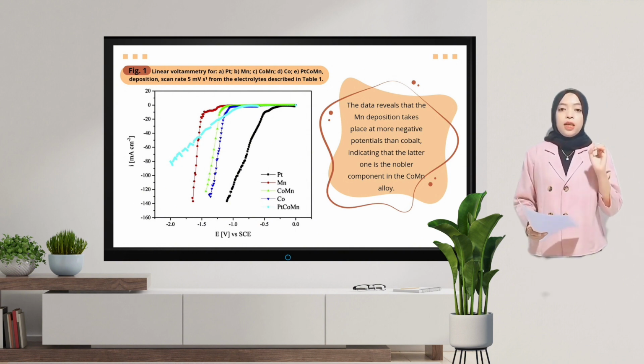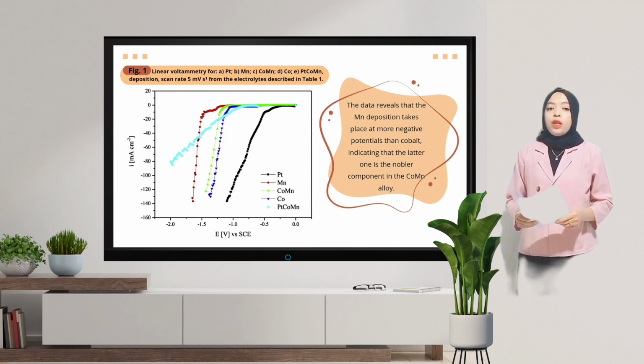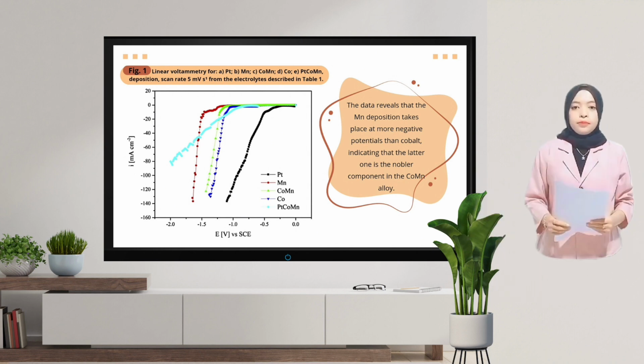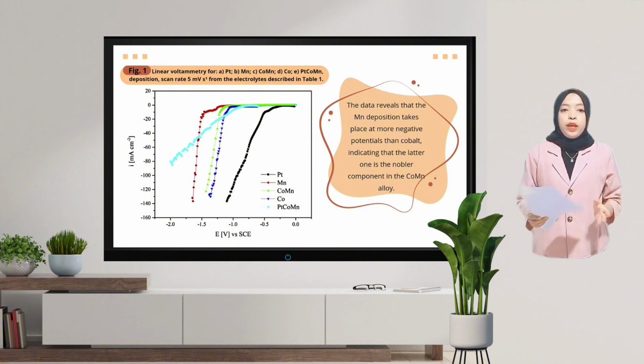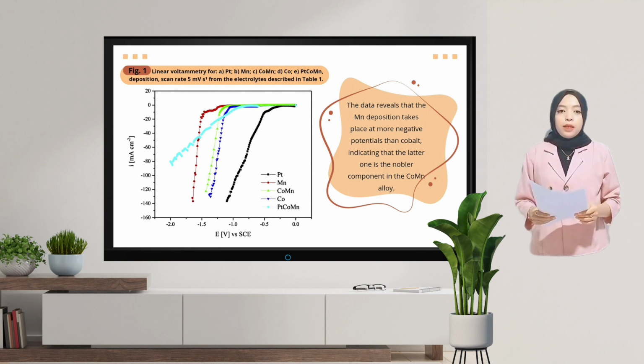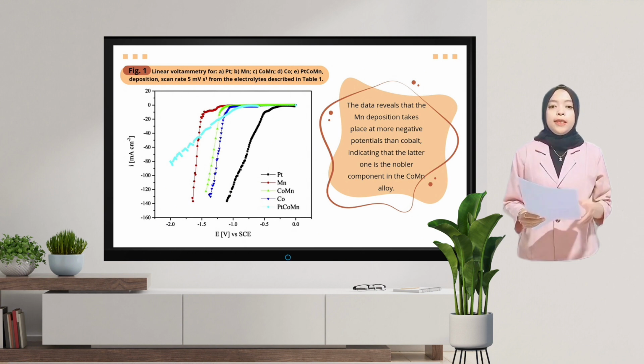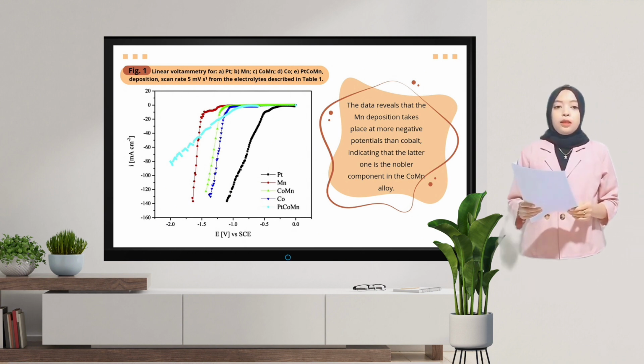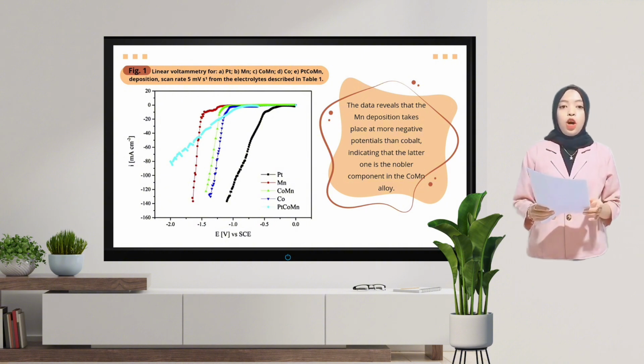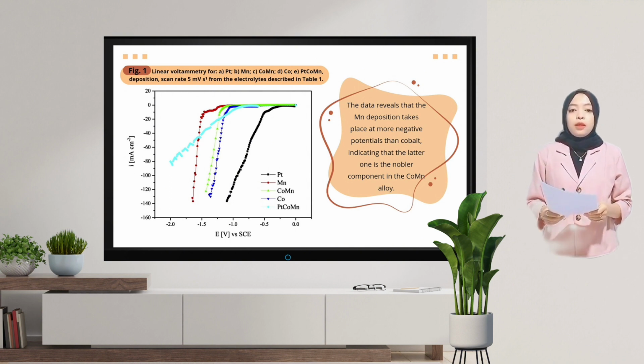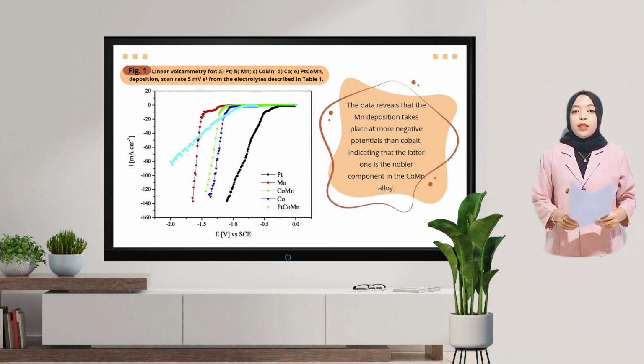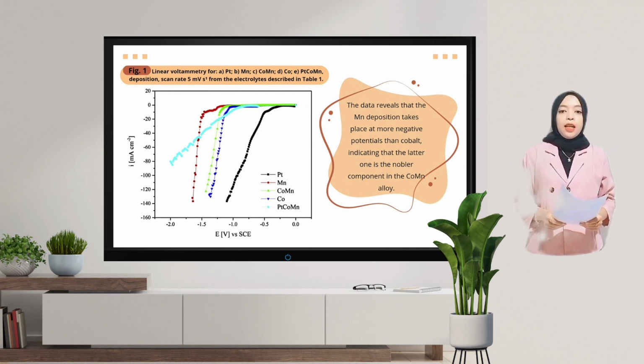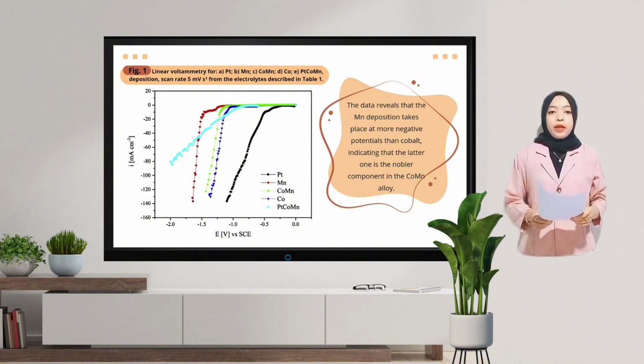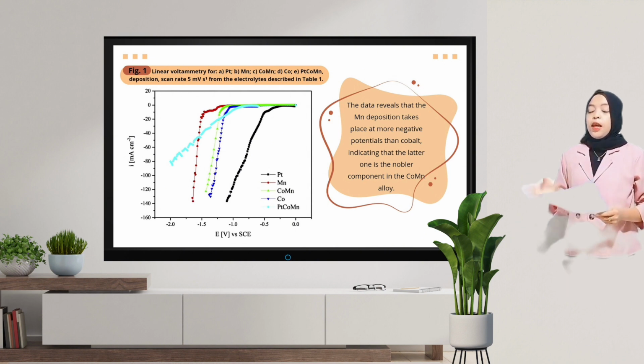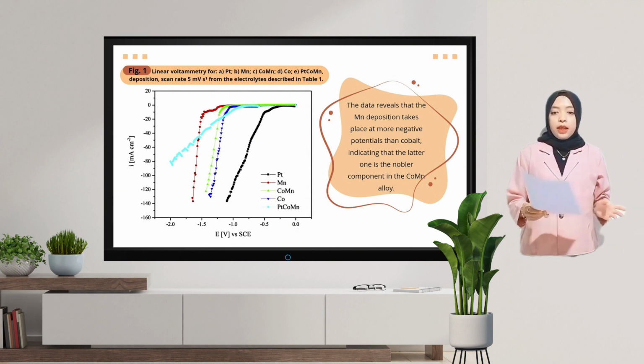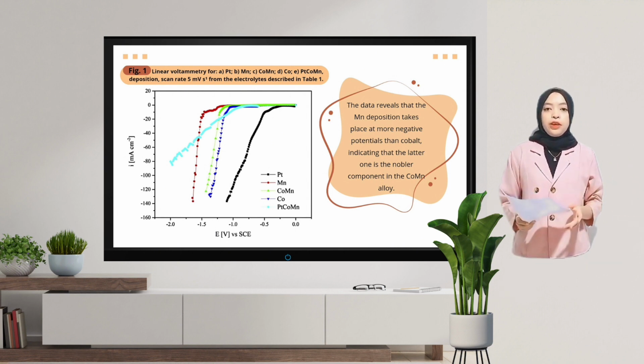Measurements were carried out starting from 0 volt versus SCE toward the negative direction with a sweep rate of 5 millivolt per second. Figure 1 illustrates the relationship between the deposition current densities of the individual elements of the ternary system and the cathodic deposition potentials. The data reveals that manganese deposition occurred at a more negative potential than cobalt, indicating that cobalt is a nobler component in cobalt-manganese alloy. The cathodic polarization curve for the deposition of cobalt-manganese alloy lies between the representative metals cobalt and manganese and resembles the cobalt polarization curve. Therefore, cobalt-rich alloys are most likely in the structure of the obtained materials.